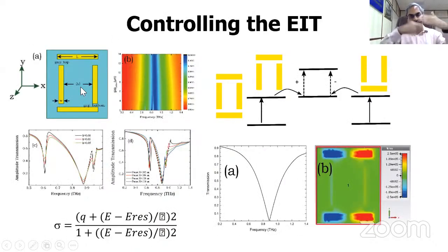So we can control how much absorption happens or how much transmission happens by introducing another horizontal nanorod under this traditional dolmen structure. By controlling the position of this bottom rod, you can induce a counter-propagating quadrupole into these two vertical rods, so we can control how much transmission is happening. We showed that in addition to the broad transmission which we expect for a single dolmen, we have this enhanced transmission here, which is happening because of the presence of this bottom rod. This is known as plasmon induced transparency, and we can control the, sorry, this question mark is gamma, which is the line width. We can control the line width or the quality factor of these modes. So we showed very high Q cavities from this.